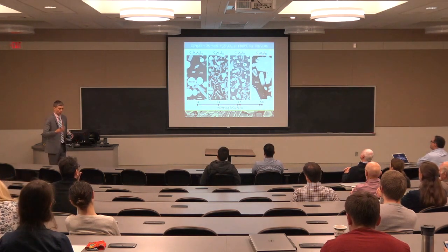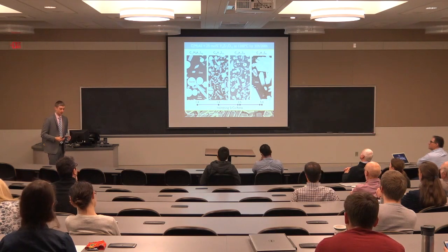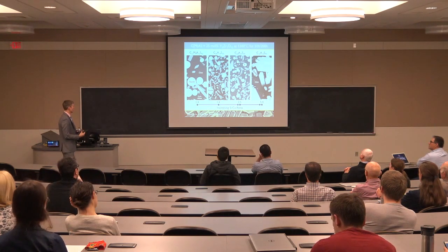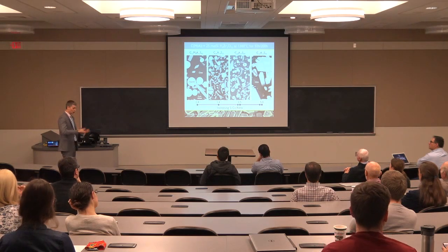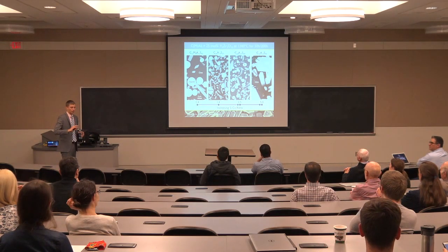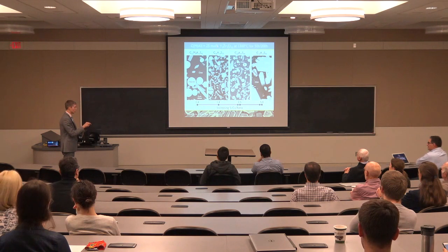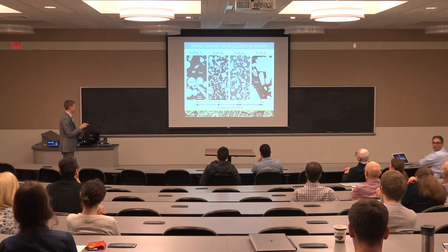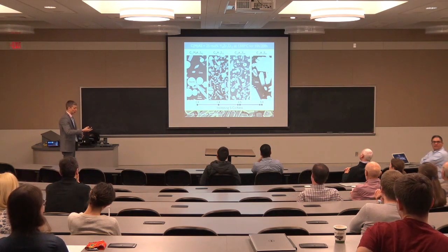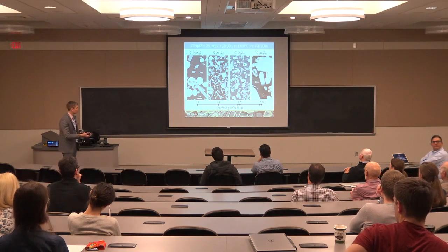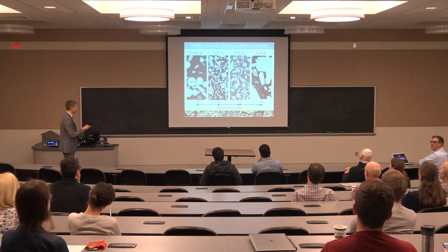The next question is, what happens if we add zirconia, since many of the coatings that are of interest are zirconia-based? And what happens in this case is that the coating material dissolves. It's a mix of yttrium and zirconia in the material called delta phase, that particular composition. It dissolves. The zirconia is much less soluble in the melt, and so it reprecipitates as this fluorite phase, which